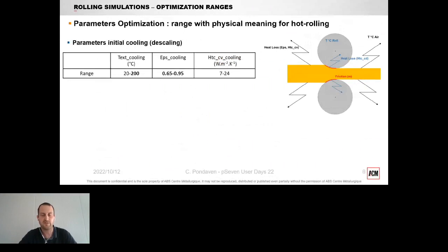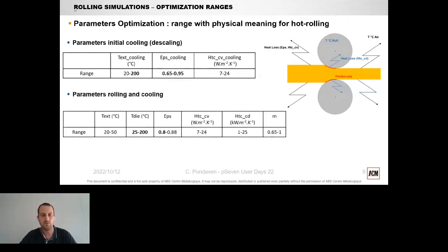So all those boundary conditions and parameters will be defined using an optimization procedure. Here we have a first set of parameters that I use to model the initial cooling performed during the descaling, where the oxide formed during the reheating phase is removed using water jets. This part is a bit specific, so we have to use a different set of thermal parameters. And then we use thermal parameters or friction parameters that are representative of the conditions that can be observed during rolling for the rest of the optimization. So to perform our simulation, we have to define 9 parameters using the optimization procedure.